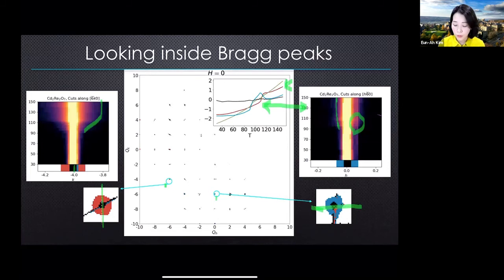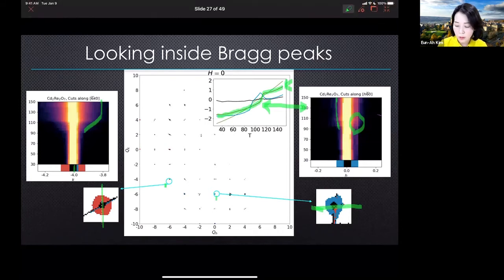not, we were able to confirm that this fluctuation, which was first observed through this clustering result of this red cluster, is indeed consistent with detection of Goldstone mode fluctuations. And this was the first instance of being able to detect Goldstone mode fluctuations from X-ray data. Of course, to be able to infer that this is Goldstone mode fluctuation required further insight from the knowledge that we had outside of what's just in the data. But the analysis is what took us to that insight.